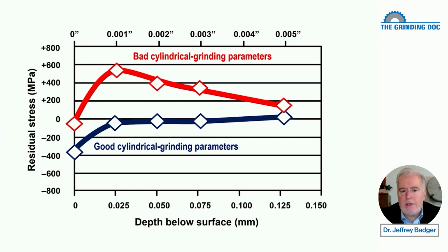So I came in, spent a couple days on the machine, or really just one day. And I said, okay, here's what we're going to do. And here's the situation. They were grinding some kind of piston shaft between centers, cylindrical traverse grinding, smaller than this. It was probably about 10 or 12 millimeters in diameter, maybe half an inch. And here's what they were doing. Here are the three key mistakes they were making.